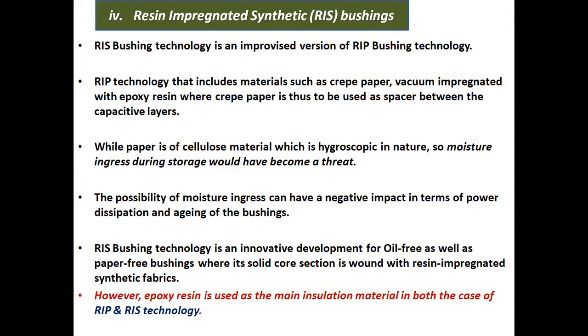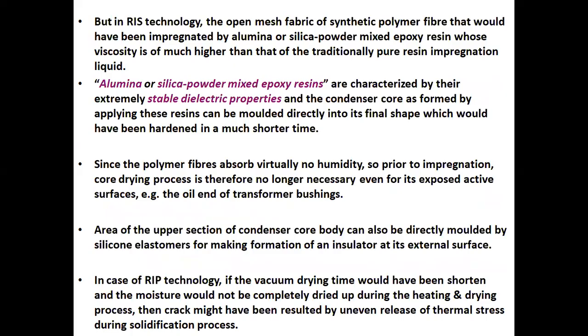Resin impregnated synthetic bushing technology is an innovative development for oil-free as well as paper-free bushings, where the solid core section is wound with resin impregnated synthetic fabrics. However, epoxy resin is used as the main insulation material in both resin impregnated paper as well as resin impregnated synthetic technology. But in RIS technology, the open mesh fabric of synthetic polymer fiber is impregnated with alumina or silica powder mixed epoxy resin, whose viscosity is much higher than that of the traditional pure resin impregnating liquid.